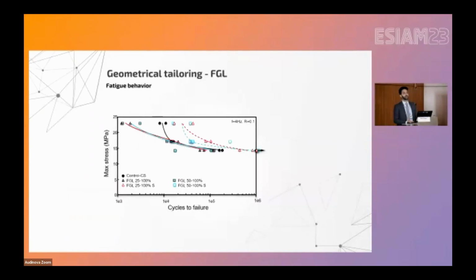Okay, we performed fatigue. This plot is a bit messy, so I'm going to separate it. First case, the tailored geometry with a relative density starting from 25%. Two cases we had: with shell and without shell. The case without shell, which is the solid red line, the fatigue properties actually got worse. We added so many edge effects that it was detrimental.